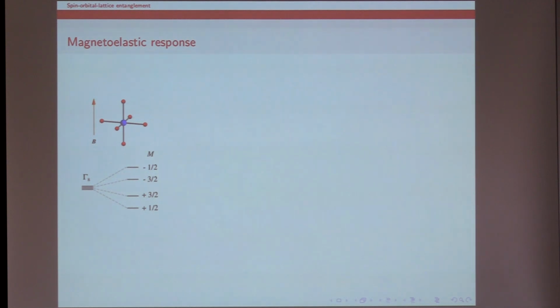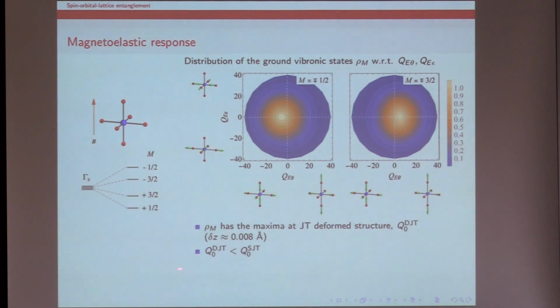We analyzed our data and we found there is magneto-elastic response. Since our vibronic level contains the information of spin also, by applying magnetic field, it shows Zeeman splitting. And we draw the spatial distribution of our wave function for each of them, and we found our wave function has a maxima at slightly deformed position. In the case of this state, we found the maximum of the distribution at slightly compressed structure. And in this case, we found the maxima at slightly elongated position.